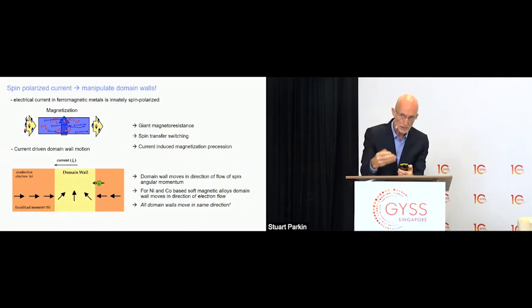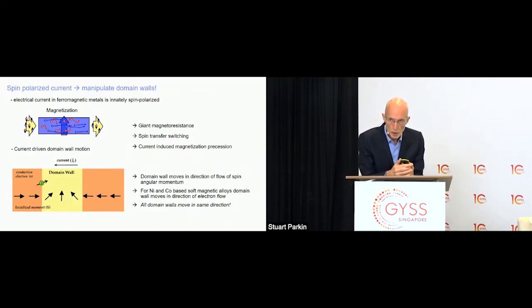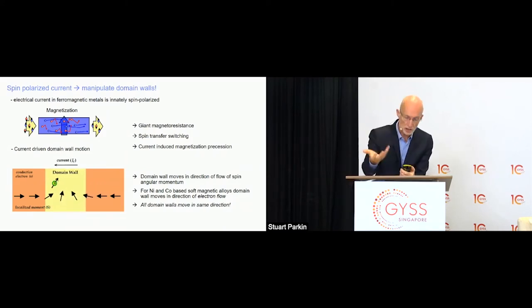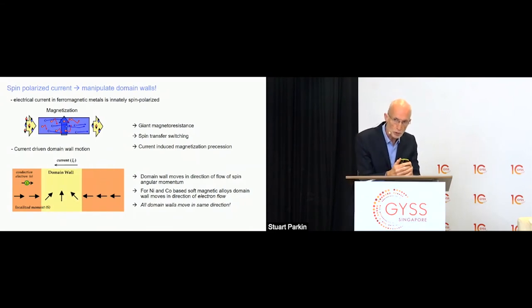Because it's conserved, this would lead to the rotation of the direction of one magnetic moment, essentially one electron per magnetic moment. So with enough current of spin polarized electrons, we can cause the moments in the domain wall to rotate and the domain wall to move.